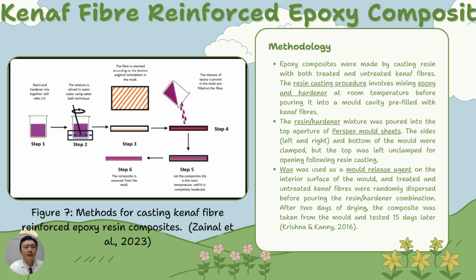Second, we will talk about the kenaf fiber reinforced epoxy composite. We will talk about the methodology. The epoxy composite will be made by casting resin and the kenaf fiber. First, the resin casting procedure: mixing of the epoxy and the hardener at room temperature. The resin will be poured into the perspex mold sheets, and then the bottom of the mold will be clamped and the top left unclamped for opening following the resin casting. Wax was also used as a mold release agent on the interior surface of the mold, and the treated and untreated kenaf fiber were randomly dispersed before pouring the resin. Then after 2 days of drying, the composite was taken.